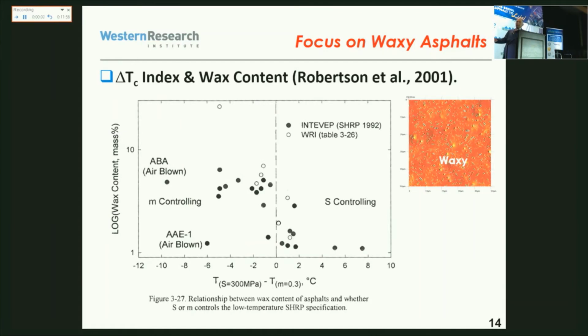And in fact, if we look at the structure of those binders under a microscope, so this is by AFM, we see that the waxy binders have this type of thing, and this was done by Troy Pauly when he was with us at WRI. And so this shows those structures, and we think that the crystals can initiate cracking, and that's not what we're looking for in asphalt.